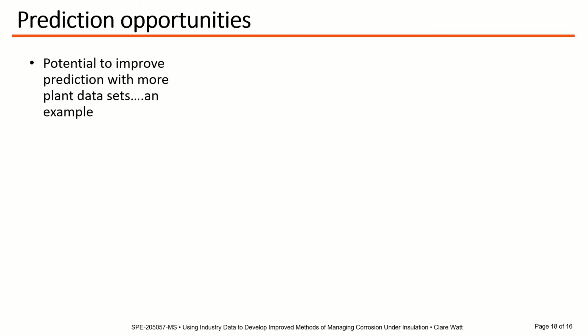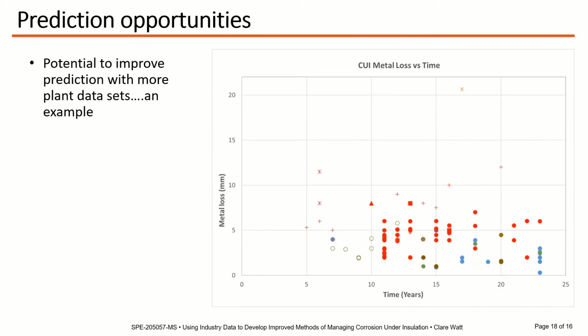This is just an example only, but here's a set of real CUI data: metal loss in millimeters versus time in years. And this applies to carbon steel CUI failures or inspection findings. There's no key, so you don't know what it means. That doesn't matter, because I do. The blue and green data shows that CUI proceeds much more slowly for equipment operating at lower temperatures, that's ambient and below, compared with higher temperatures.